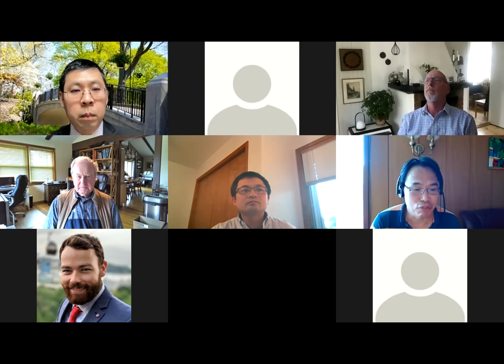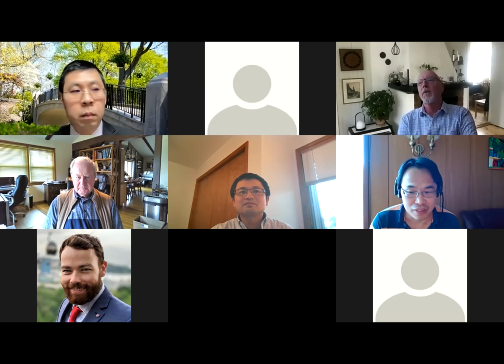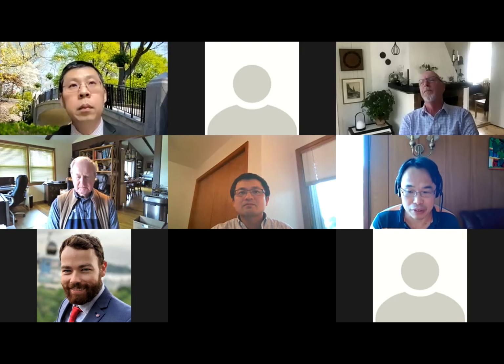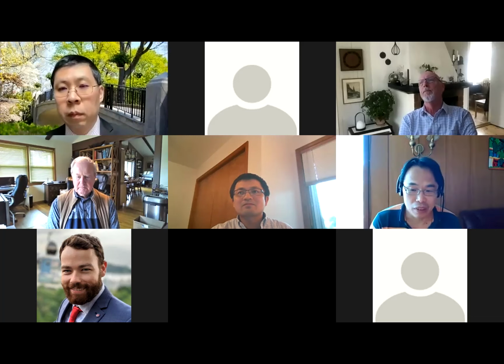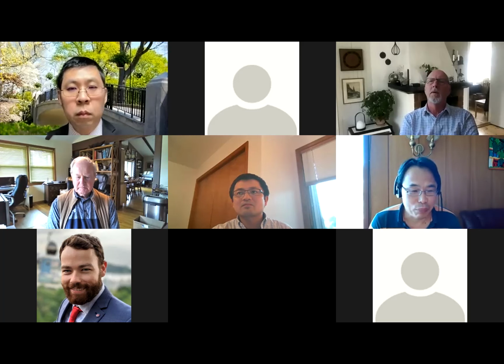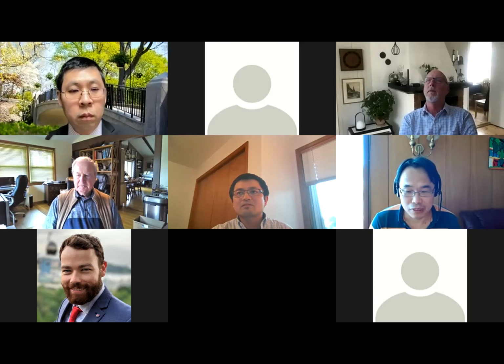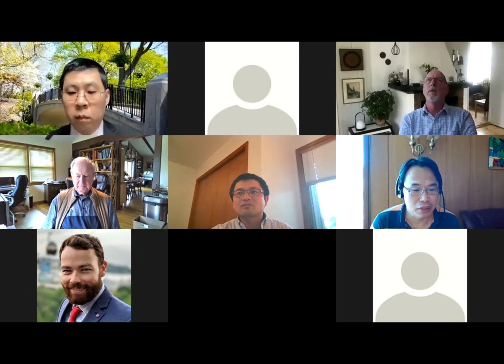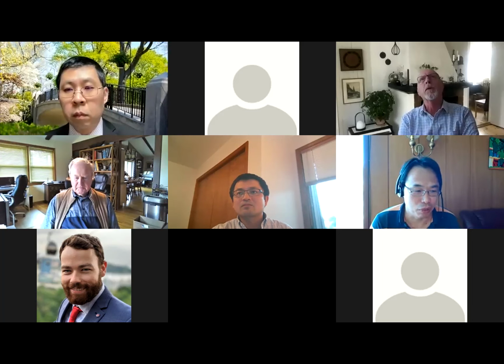Yes. Thanks for the wonderful talk. And actually, I have been reading the two papers John and Professor Liu published quite some years ago in 1989. It's about the calculation of the kinetic interface conditions at a fast migrating austenite and ferrite interface. I don't know if John, you can quickly recall the paper you published in 1989, and so it's about the calculation of a kinetic phase diagram. So it's not the equilibrium phase diagram, and I want you to comment on one of the parameters this model used, the so-called trans-interface mass transfer parameter, if you remember.